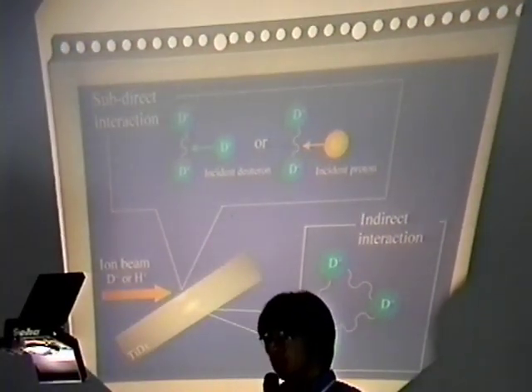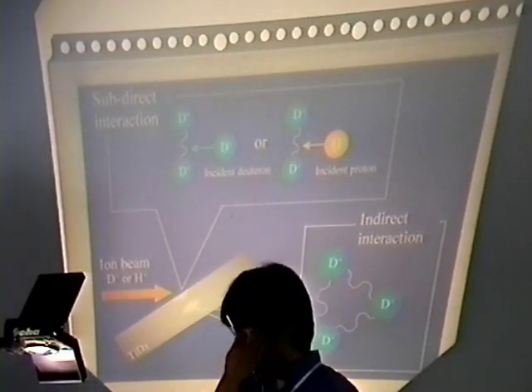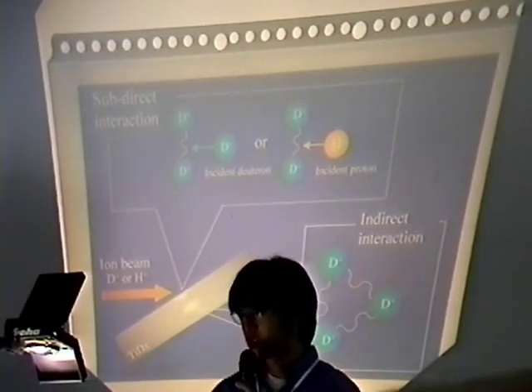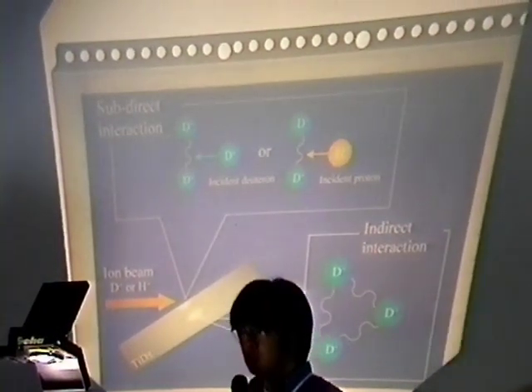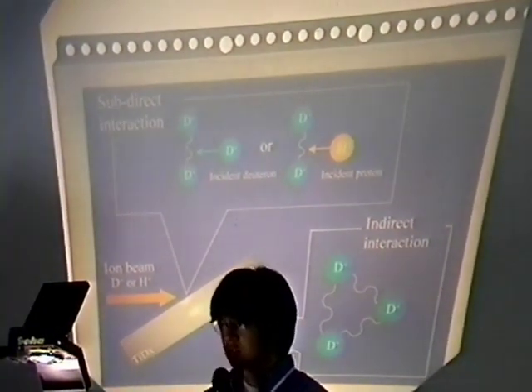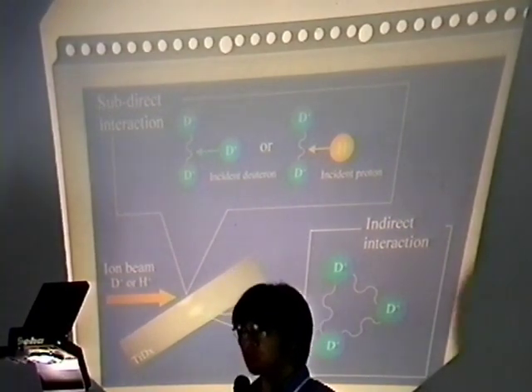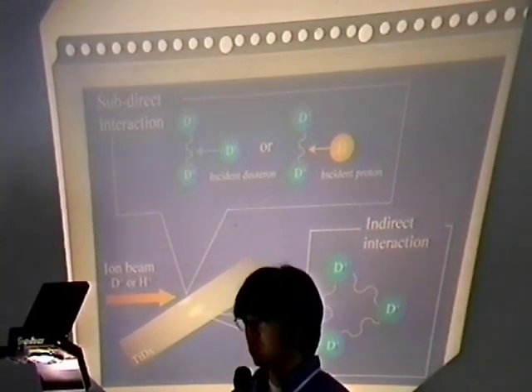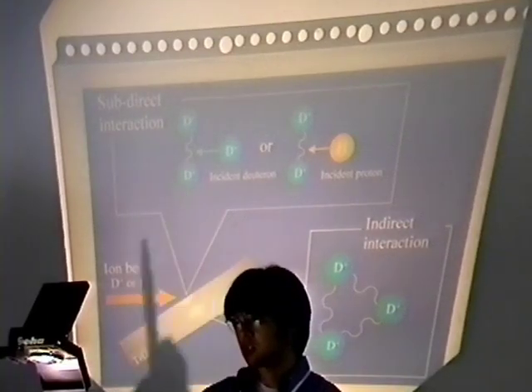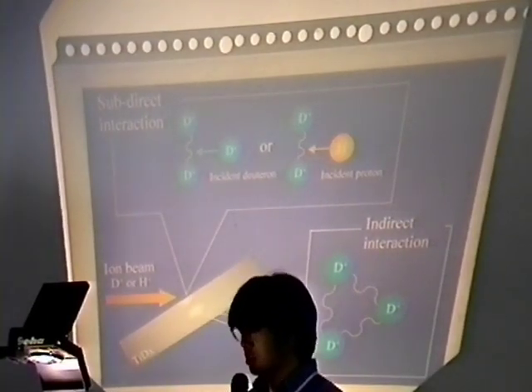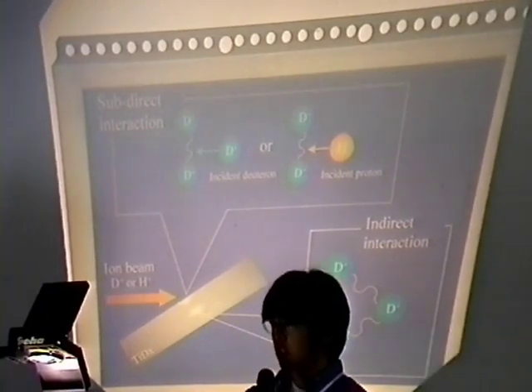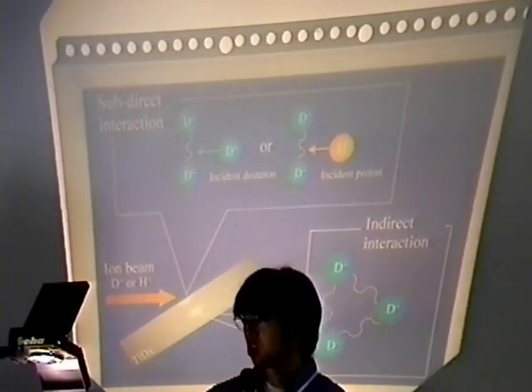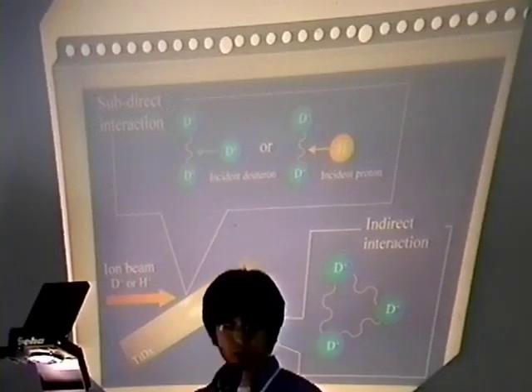From these experimental results of the ion beam experiment, in the surface region of the target, so-called sub-direct interaction took place. First, DD pairs were produced, then an incident deuteron or proton hits to induce DD reaction or HDD reactions. And at a deeper place in the target, indirect interaction of 3D reaction was induced.